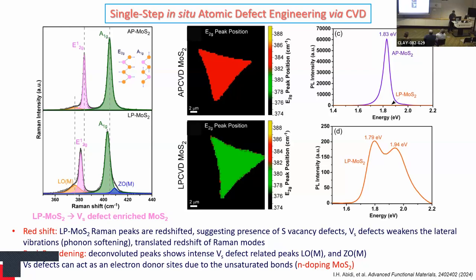So what happened once we grow with the low pressure CVD technique is that we are creating some sulfur vacancies in the MoS2. Some of the sulfur is removed during the growth. But if we have an oxygen-rich condition like APCVD, those sulfur vacancies will immediately passivate with oxygen. So these are two different types of growth conditions. If you have only low pressure CVD, sulfur vacancies are created and they will retain themselves. So then you will have this kind of properties.